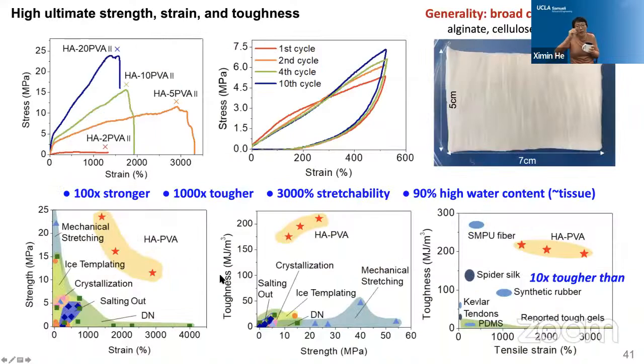With this, we summarize the mechanical properties from the mechanical measurement. Overall, the gel made from this method can be 100 times stronger than the previously reported tough gels, and 1,000 times tougher, while being stretchable to 30 times its original length. At the same time, it maintained a high water content around 70 to 90%, similar to the tissue.